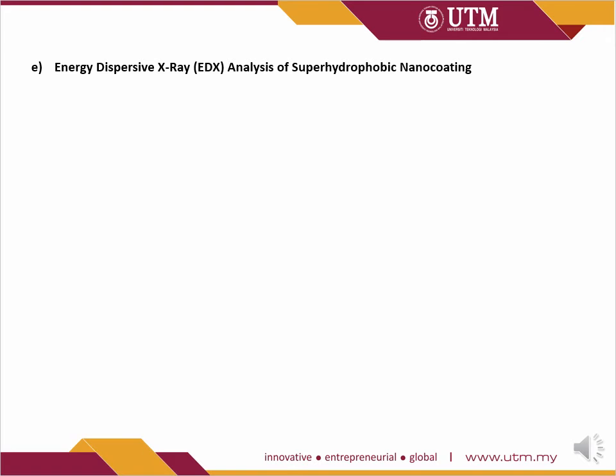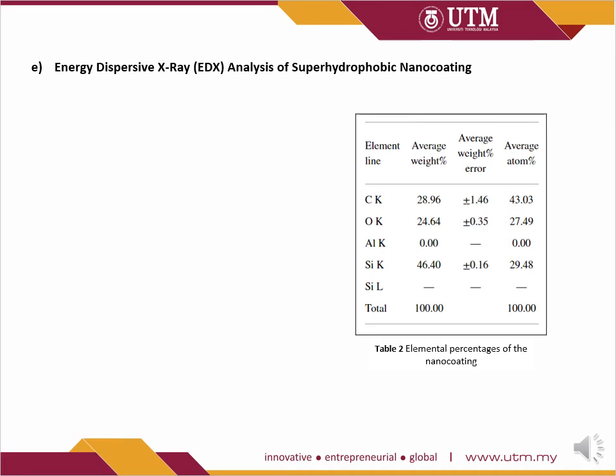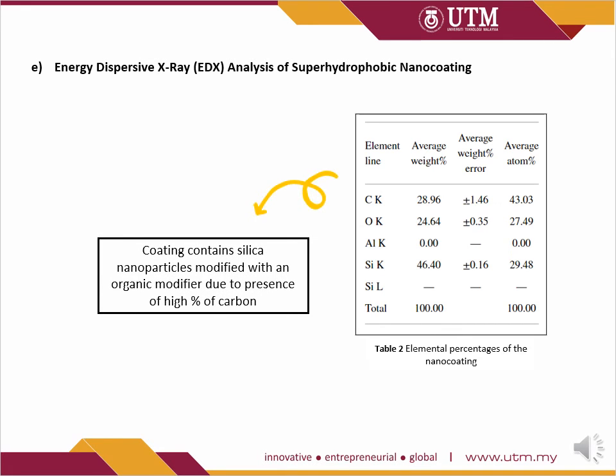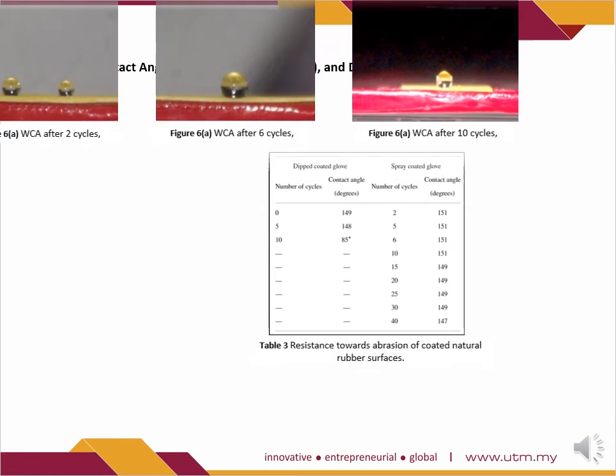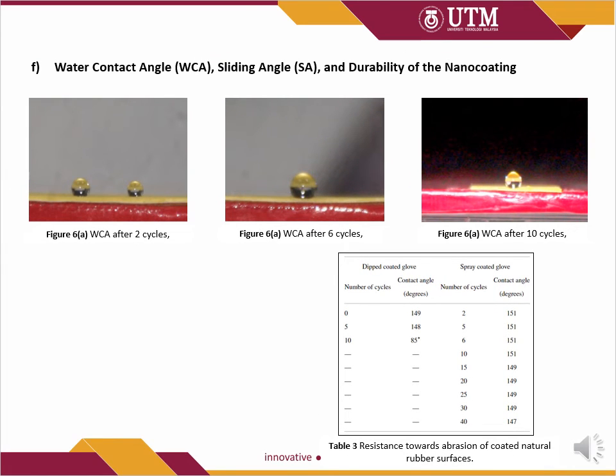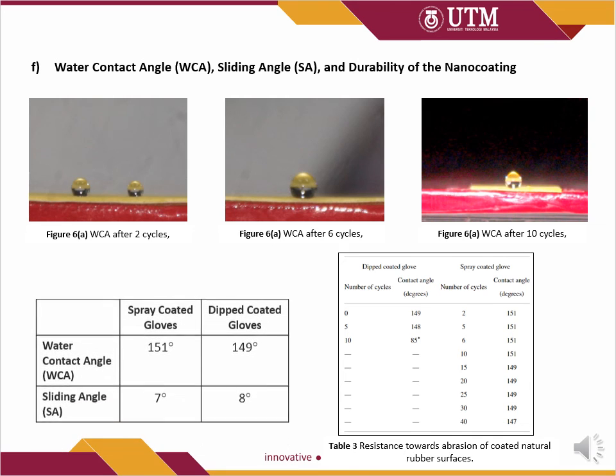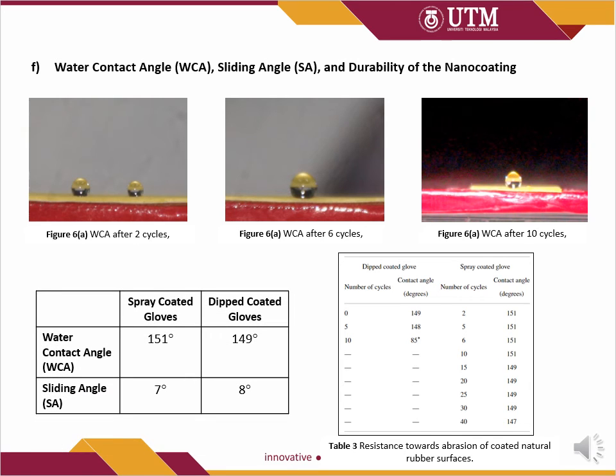Next is EDX analysis of superhydrophobic nanocoating. Based on the results shown in Table 2, it is possible to conclude that the coating does not contain any fluorinated compounds. Moreover, the presence of a high percentage of carbon confirms that the coating contains silica nanoparticles modified with an organic modifier. Next property is the durability of the coating, which was measured by recording the resulting water contact angle after each abrasion cycle, shown in Table 3 and in the figure above. The initial water contact angle was 151 degrees and 149 degrees for spray and dip coated glove.